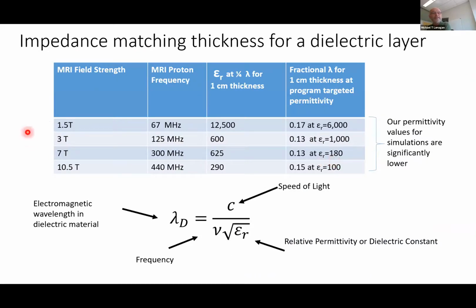I won't get into it today, but we've explored this concept with all these different MRI units, going from 1.5 Tesla to 10.5 Tesla MRI units. And what that means is that our proton frequency, our RF frequency, goes from 67 all the way up to 440. And we've actually tried these different pads on each of these systems. And we found generally that we need to be in this wavelength range, about 1/8 of a wavelength in the dielectric pad, that gives us the optimum result. So it's just another way to look at coupling this RF wave into the body from a coil.